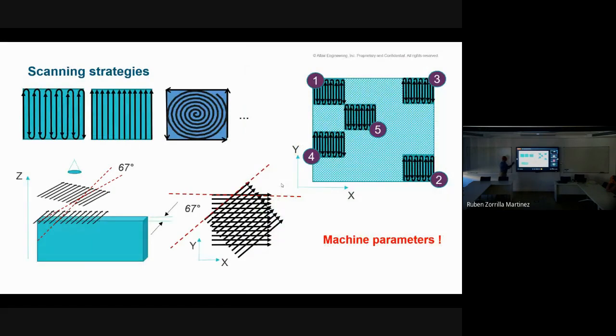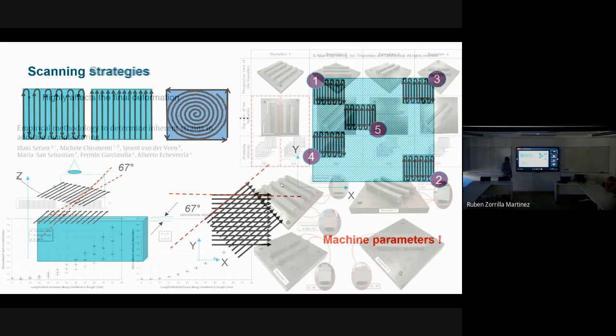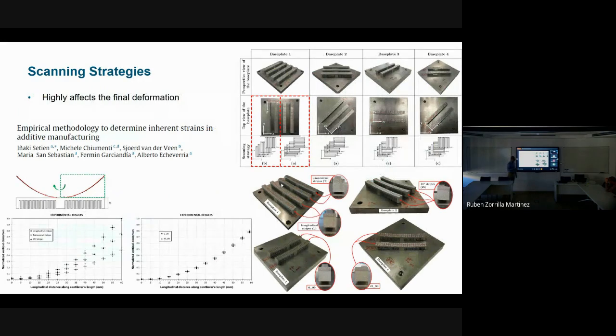For the scanning strategies, there are many, like sequential, one way, but nowadays the one that is usually used is this one. They put one direction in one layer and then they rotate, maybe 67 degrees, which is the standard one, or 46, I think. Then they rotate and do another one, and rotate again. Why? If you go to the literature, and here, Michele is again here, you can see that this is the same geometry that they were printing in different ways, with different directions and different patterns.